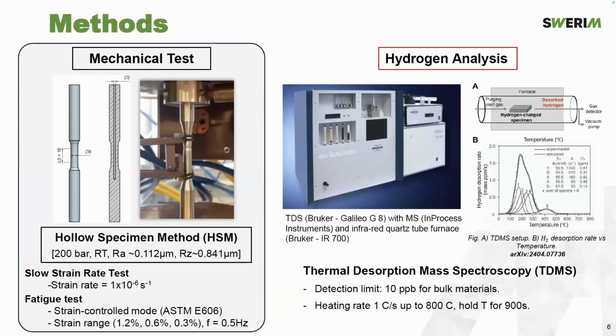The method used is the hollow specimen method. We use 200 bar pressure at room temperature. We polished the inner surface to 0.1 micrometers. We used a slow strain rate test, with a strain rate of 10 to the power of -6, and a fatigue test in strain control mode, following this standard, with 3 different strain amplitudes at a frequency of 0.5.